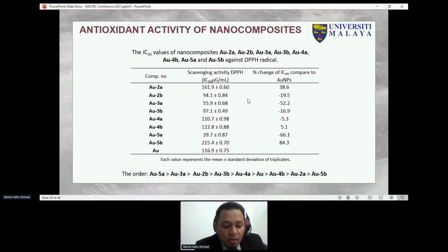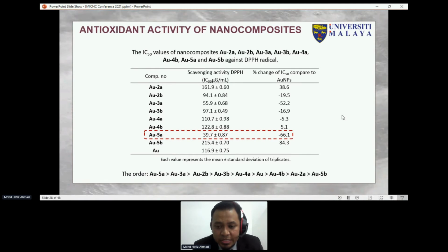Next, all data are supported with antioxidant activity results to show that the functionalization of ligands on the gold surface is successful, not only for mono BHT ligands, but also for dimerization of BHT ligands. All nanocomposites show strong antioxidant activity with lower IC50 value than standard gold nanoparticles, except nanocomposite 2A, nanocomposite 4B, and 5B, which show moderate activity against DPPH radical. Nanocomposite 5A shows the greatest inhibition, with a 66.1% decrease of IC50 value compared to gold nanoparticles.